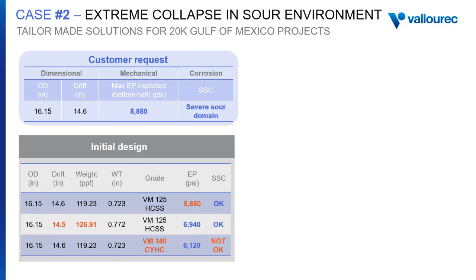The only alternative left was to move to a higher non-sour grade. We see that by keeping the original weight of 119 pounds per feet and switching to a VM140 CYHC grade, we are able to achieve a collapse rating higher than the minimum requested. However, this grade does not offer sour service resistance, and the risk of having a failure due to sulfide stress cracking is considerable. So, in one word, there was no solution at the time for these customer challenges.